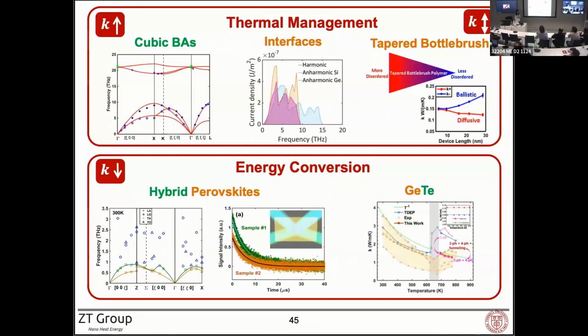Yeah. I have a question on the last part on GeTe. So you say that you fit the potential up to a Taylor expansion to get into your force constant the effect of temperature. But if you imagine to go to an infinite series, so to have all the possible anharmonic terms, so to expand this series at infinite, this doesn't depend anymore on temperature. So it seems a bit contradicting the fact that the more terms you add in your anharmonic expansion, the less they depend on temperature. So the phonons also that you get, even the harmonic expansion, depend on successive terms that you include in this expansion. So how does the thing get in?